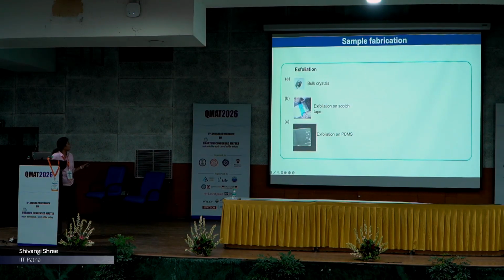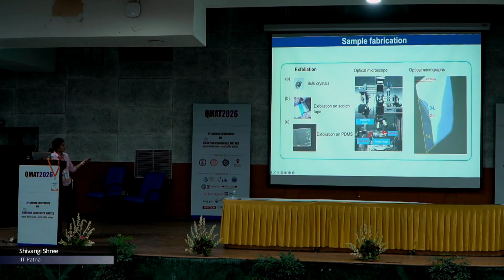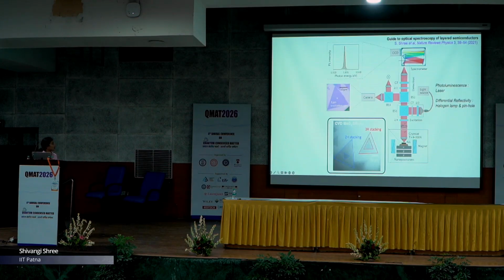This is the part where we do exfoliation, then just transfer this on. This is a home built setup that I used, and in the optical microscope you can identify the layer thickness. Of course, AFM or PL will be useful to further confirm the layer thickness. But just by contrast, because these have very high absorption, at first glance you can see whether you have a monolayer or not.